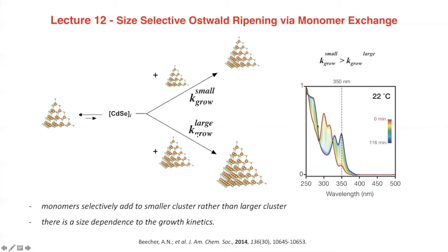And so in the middle of this reaction that we're running here, where this one's going away and this one's appearing, in the middle, you have an equal amount of both the small cluster that's dissolving and the big cluster that's forming. And so those units now have a choice as to whether they're going to deposit on the smaller pyramid or the larger pyramid. And because of the fact that this is so selective for this next size, as long as you keep the temperature low, it must be true that these units preferentially adsorb to these small clusters over the large ones.